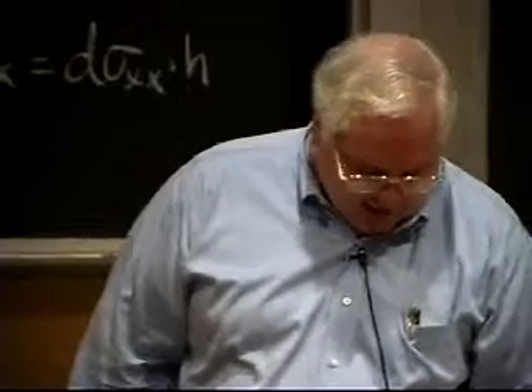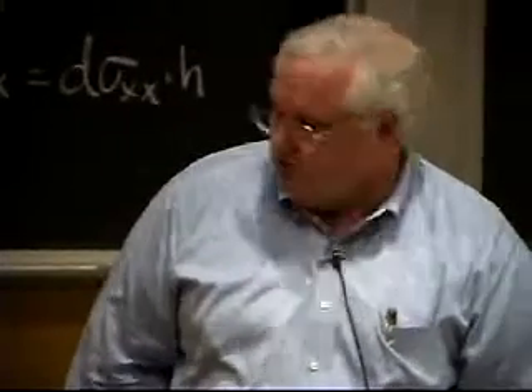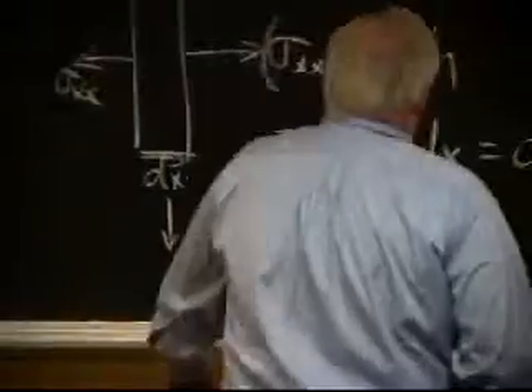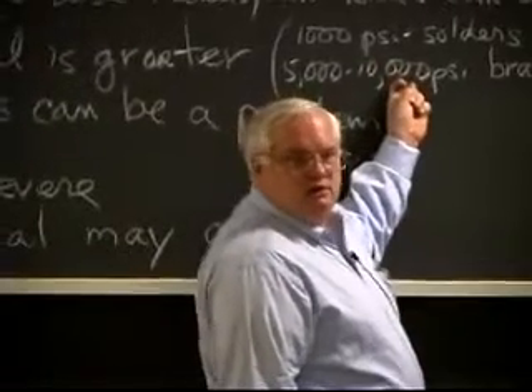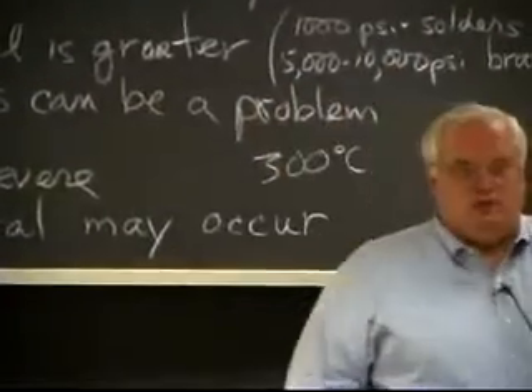But in a joint that's designed for some tension, it does effectively give you some significant increase in strength of a braze joint. Okay? Of contact strengthening? It's basically just the fact that braze joints actually outperform what you would predict otherwise. If you go and look at the base material strength of the braze alloys, you wouldn't necessarily get all of this. It might be a 20-30% increase in overall strength of that joint. And so what's the practical industrial application? Really none if you just go out and pull joints and say this is the strength. If you want to scientifically explain why I'm getting that strength, you have to understand contact strengthening to realize that it's really there.